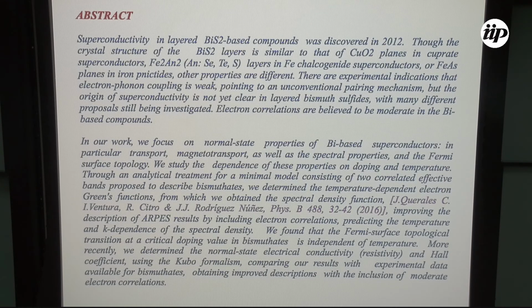And there have been many discussions, of course, quickly after they were discovered, about the origin, which could be the mechanism for the superconductivity. There are many indications that the electron-phonon coupling is weak, even though the Tc is relatively small, as I will show. Electron-phonon is too weak to provide the kind of coupling which would result in the superconductivity seen. And there have been many different proposals, among them the effect of electron correlations.